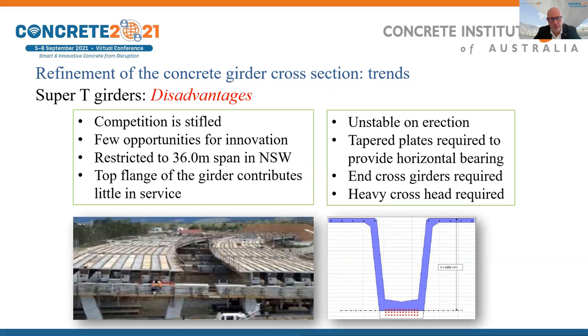In addition, these girders are very unstable on erection and need careful bracing through the erection process. There have been instances where Super T girders have toppled over during construction. They require a tapered plate to provide a horizontal bearing surface between the sloping soffit and the top surface of a horizontal bearing. In some state jurisdictions, heavy end cross girders are required, which certainly takes away from the cost advantage. And invariably, there's a large, heavy crosshead required, which adds cost and indeed detracts from the appearance of these bridges, particularly in viaduct construction.